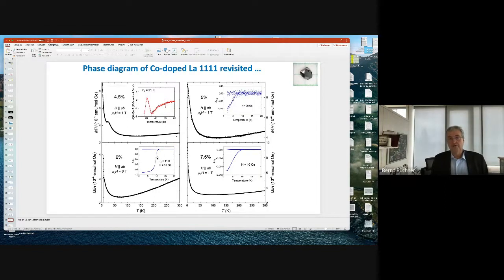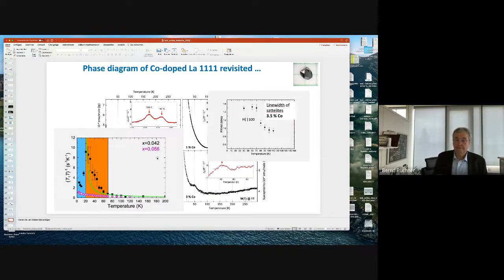We also followed these phase transitions by microscopic probes. So this is NMR measurements where you can see for, let's say, 4%, you still have this strong increase of the relaxation rate telling you that you enter a magnetic state. Whereas if you go to higher doping, this peak disappears. So we have the border to non-magnetic state.